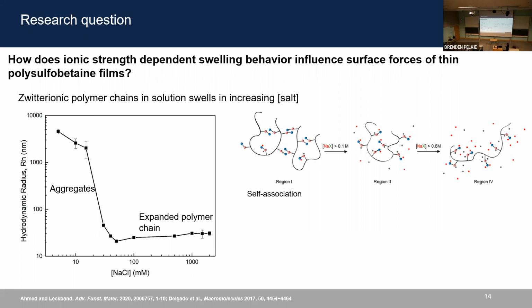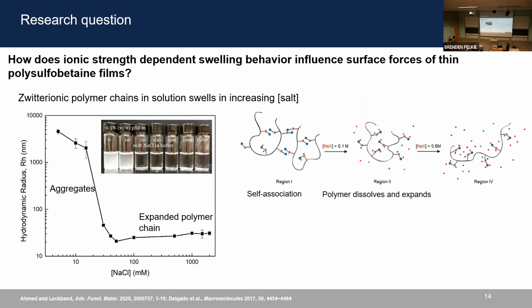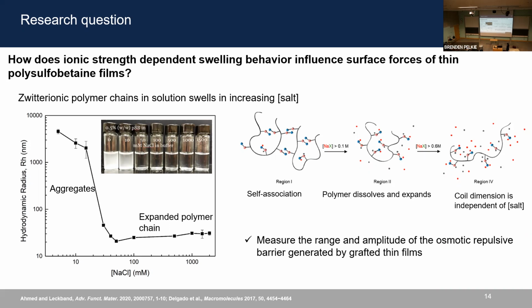And as we add more and more salt, the coil dissolves and starts to interact with the charged side chains and expands. And so here, after reaching a minimum, it expands further, and we can see it visually also. And the coil dimension eventually becomes independent of increasing salt because there is now a chemical equilibrium that is established. So in this project, we wanted to see how the range and amplitude of the surface forces are affected by the swelling dependent behavior of the polysulfobetaine chains.